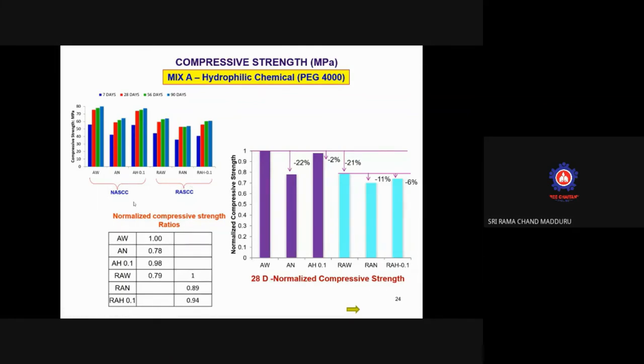in bulk. And in case of recycled aggregates, if you compare AW and RAW, that is natural aggregate concrete and recycled aggregate concrete, there is a 21% reduction in strength. This 21% strength reduction is due to the material. If you compare natural aggregate and recycled aggregate, the poor quality of recycled aggregate is leading to the reduction in the strength. However, when you observe, this recycled aggregate is also acting as an internal curing agent. When you compare AW and AN, there is a 22% reduction.